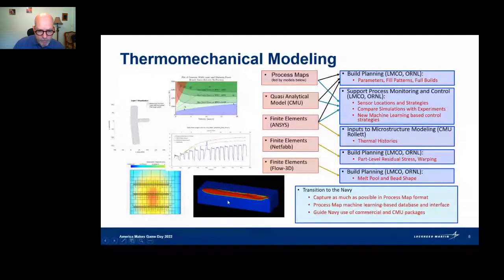And so the essence of doing that is, in order to understand the thermal history, once you have that, now that all feeds back into the models that Tony Rollett's group uses to do the material state, to understand what the morphology is within the specific areas within that part. The thing about the thermomechanical modeling is that it also helps us to understand a reasonable scan strategy for a part, or an optimal scan strategy for a part. So these thermomechanical models would help us to predict both distortions and residual stresses, as well as feeding that thermal history into the material state models.